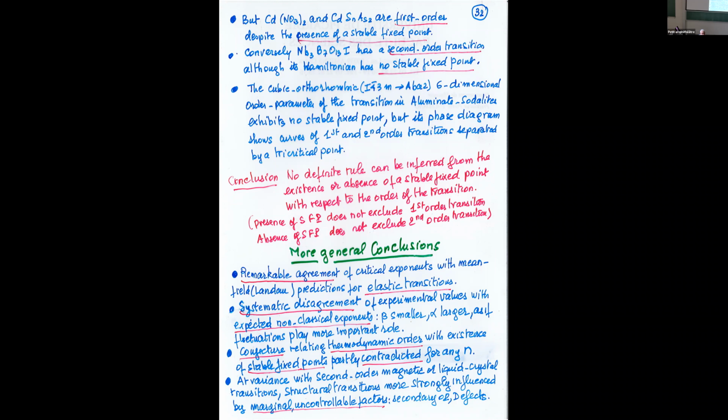Liquid crystal, it's another story. It's a very interesting story. And by the way, since it was mentioned, the exotic phases: you asked me today a question in the discussion if I knew a phase transition where you have a sixth-degree term associated to a second order phase transition. In exotic phases, precisely, the symmetry breaking term is a sixth-degree term in the Landau expansion. You don't have a fourth degree. The fourth degree term is isotropic, and you have to go to the sixth degree to have the possibility to break your symmetry.